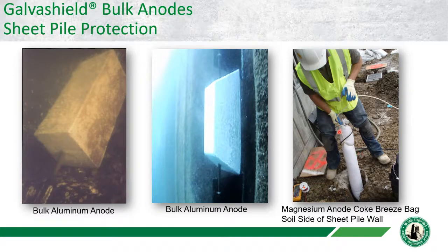The magnesium anodes are inside of this bag, and this whole package keeps the magnesium anode active. And one thing to note is this type of anode is used on the dry land side of the sheet pile wall, the opposite side of the water. So if you look here, there's a sheet pile wall, and you can still get corrosion in those soils. A lot of those soils are going to be corrosive, and so you will have corrosion on the front side, or the water side, and the land side. So putting in the magnesium anodes on the back side is going to provide protection on the back side also.